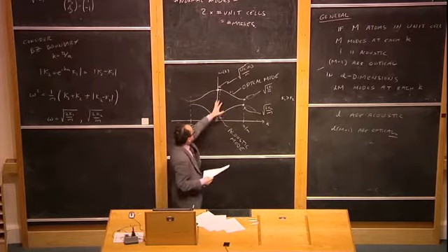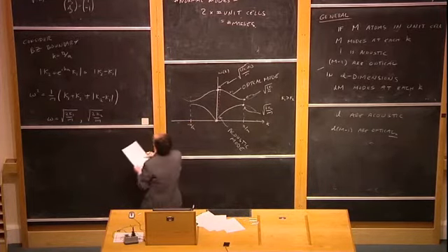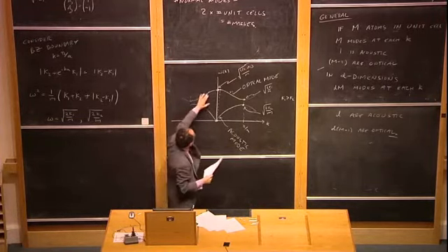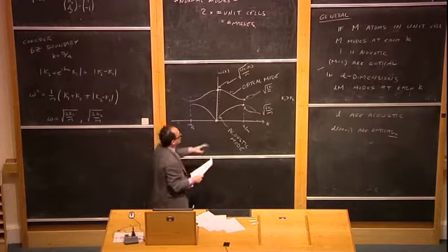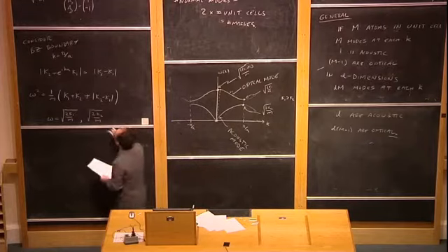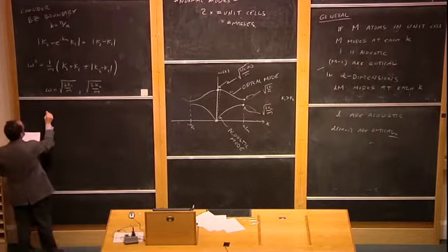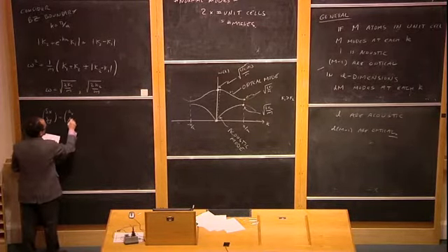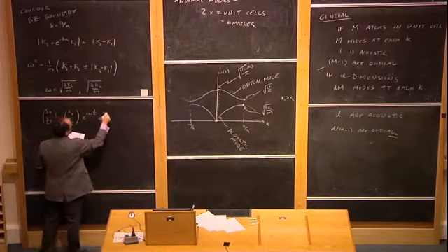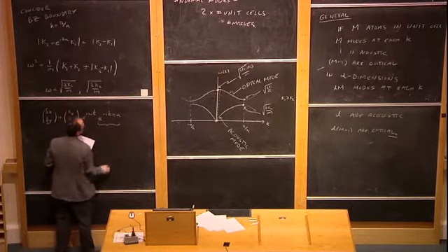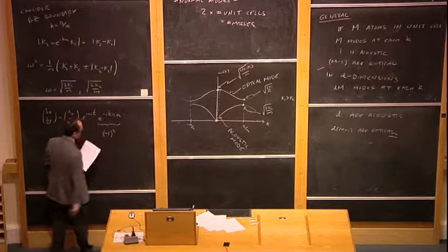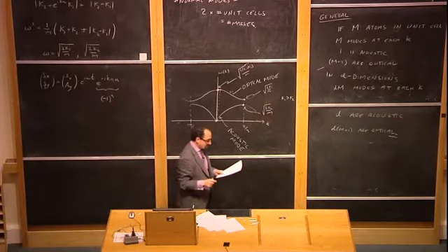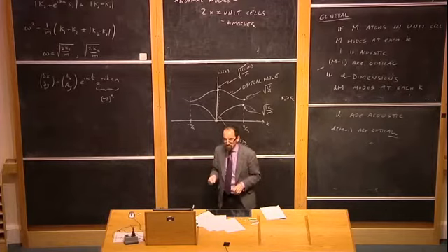Otherwise, it would be the other way around. The higher energy one is always on top. And these modes actually never cross each other. You can convince yourself by looking at the form of the frequency. These two modes can never actually cross. So what's going on at this Brillouin zone boundary? At the Brillouin zone boundary, the waveform delta x delta y equals ax ay e to the i omega t e to the minus i k n a. This e to the minus i k n a becomes minus 1 to the n. And that tells us that alternate unit cells are moving out of phase with each other. They're moving in the opposite direction as each other.